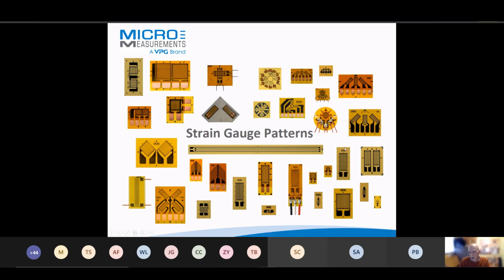output. If you want to use a linear strain gauge, you need to know which direction to put the gauge, whereas if you use a three-element rosette, you can resolve by maths the actual principal magnitudes and directions. So if you don't know direction, a three-element rosette is ideal. We have T-rosettes, great for material property testing that I'll mention a bit later on. And we also do residual stress gauges, where you drill a hole and measure the change of strain due to the relief of stress, and then you can calculate the stress that was in the part before you drilled the hole. We also do a range of weldable strain gauges that we'll mention later, and the grid sizes can be anywhere from 0.2 millimeters up to over 100 millimeters. This is because a strain gauge is an averaging device. If we're working on concrete, we want to get an average strain in the concrete and not a local strain on or near one of the lumps of aggregate. So there are many thousands of different patterns that you can choose from to suit the application.